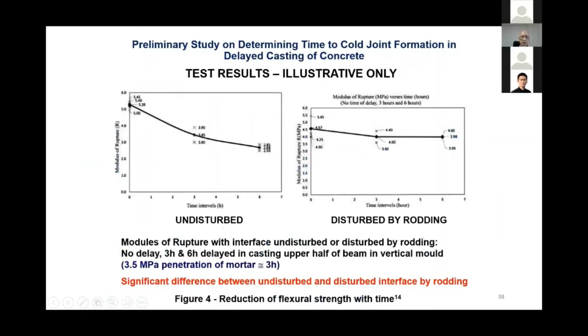If we do not disturb the surface, it falls off very rapidly. Now that means this would be a situation if you are placing SCC. You don't even have a vibrator on job site, so obviously you don't disturb the interface. You just continue pouring concrete down. But if we disturb it in our method, you can notice a very small change.